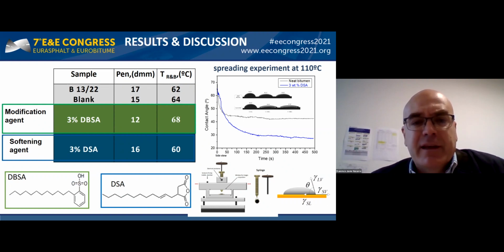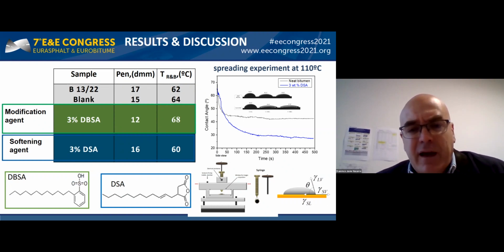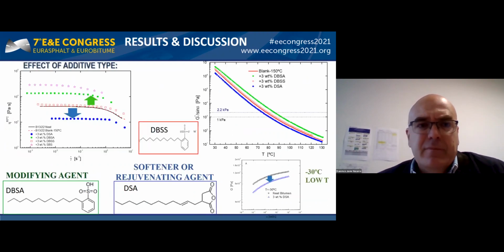By contrast, the alkenyl succinic anhydride, DSA, produces an opposite effect, revealed by the subtle penetration increase and a clear drop of 4 degrees in ring and ball softening point. Consequently, DBSA appears to us as a stiffening agent, whereas DSA seems to produce a softening of the binder after modification.